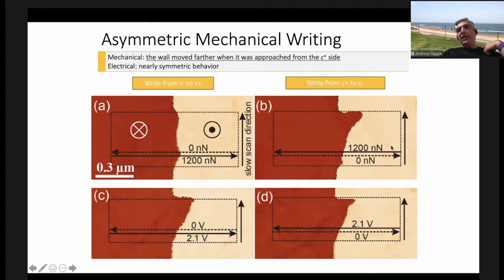And then they do the reverse experiment. They put the tip down hard on the P plus domain and they drag it to the left. Then they raise it so it's not doing anything and they bring it back to the right. Then they push hard and they drag it to the left. And look how different the domain wall is. Can you see that as they did this rastering to the left, the domain wall moved way further than it did when they rastered to the right? You might think, who cares which direction you start first? But it makes a huge difference. I think this is quite an interesting experiment. And so we did some modeling in order to examine this.